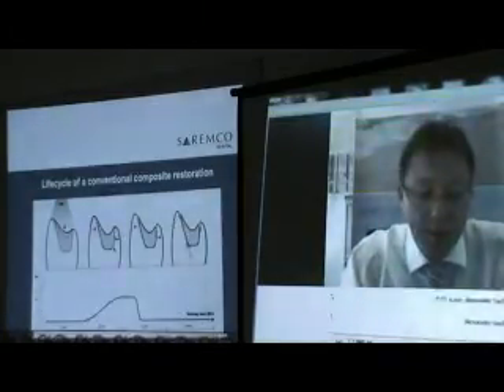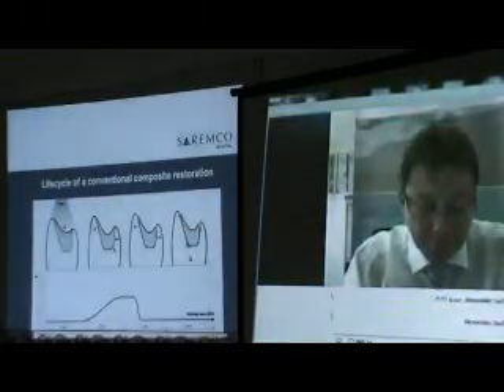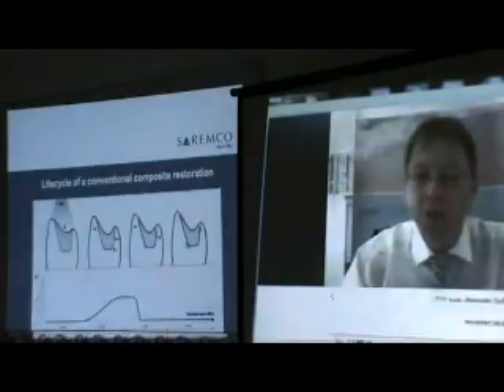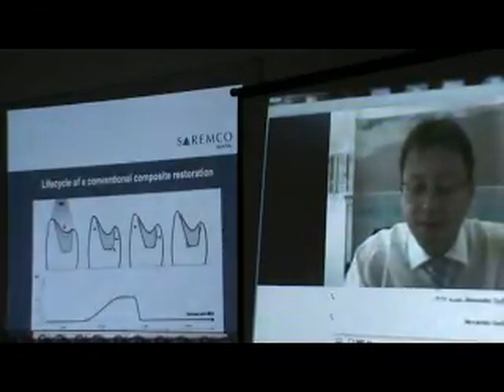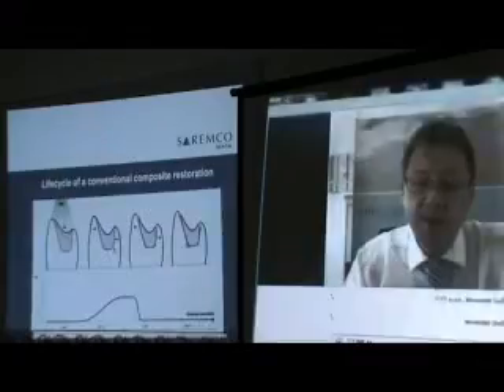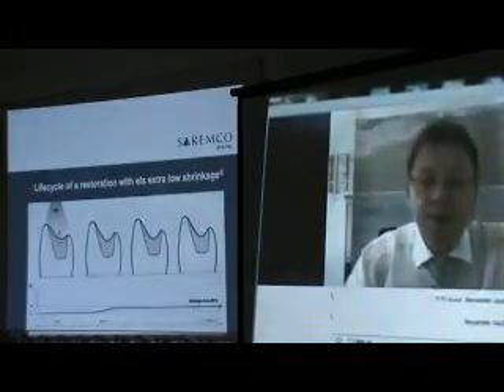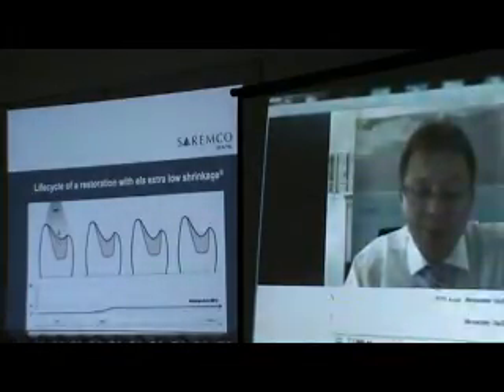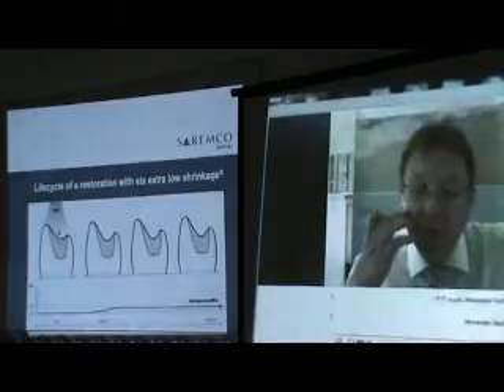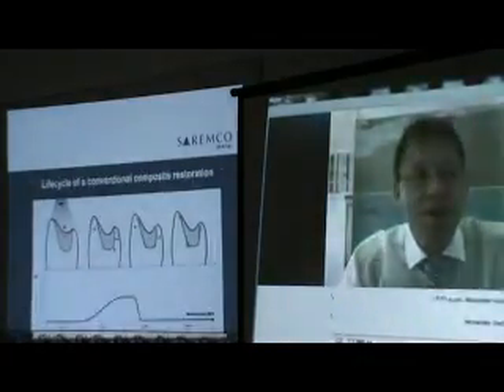It can actually lead to sensitivity of the pulp due to the deformation of the dental cusps, even if it is only a few microns. A few microns is enough to create cracks in the natural enamel and maybe create sensitivities of the pulp. But there is also a problem in the long term when you have high shrinkage stress, that you see in picture 3. After a certain time, the bonding is maybe not strong enough anymore and it can lead to opening of the margin due to the fatigue of the adhesive and due to the shrinkage stress.